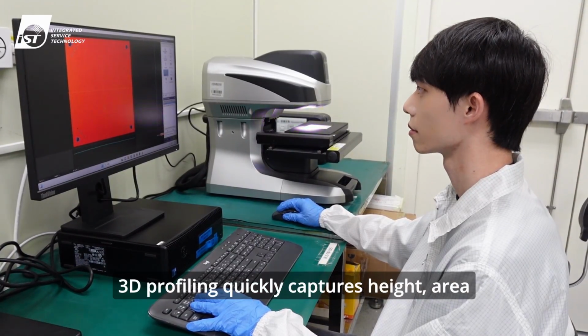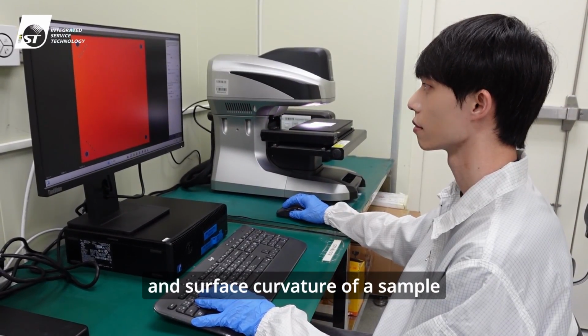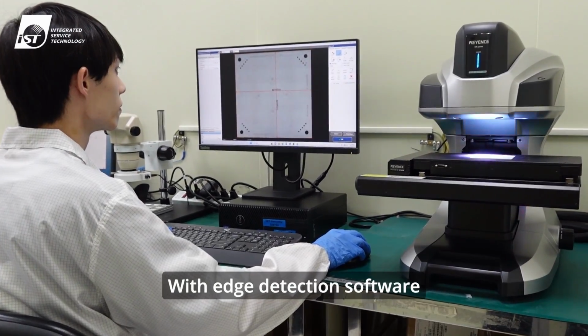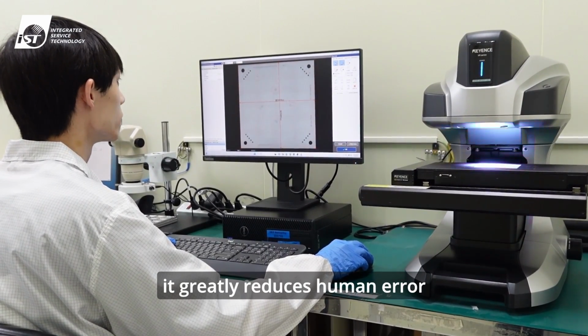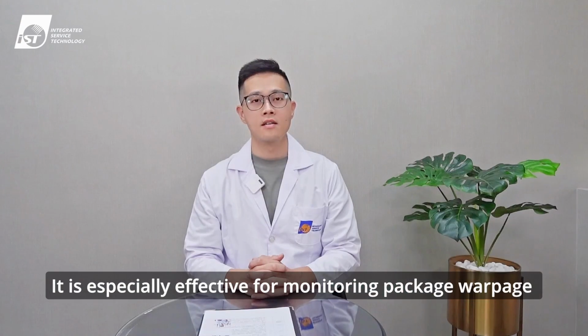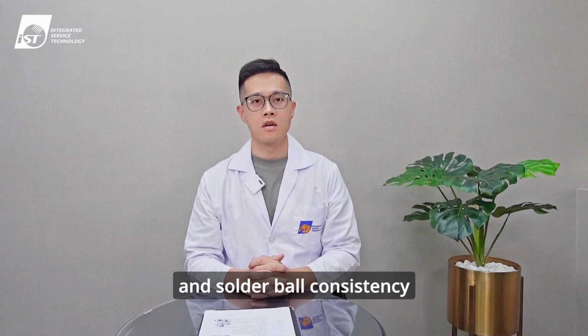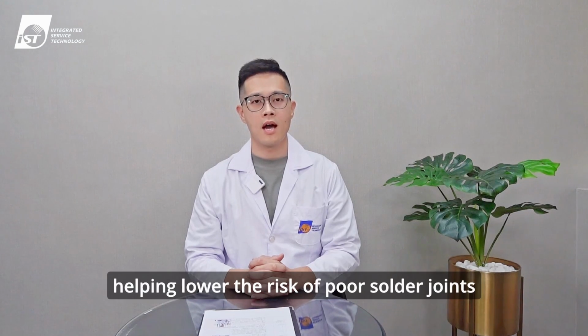3D profiling quickly captures height, area, and surface curvature of a sample. With edge detection software, it greatly reduces human error. It is especially effective for monitoring package warpage and solder ball consistency, helping lower the risk of poor solder joints.